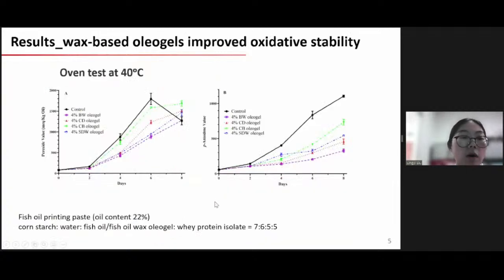Then the fish oil oleogel was used to print the shape. We can see here that by formulating the wax oleogel into the printing paste, the production of the primary oxidative products and secondary products can be reduced during the oven test.